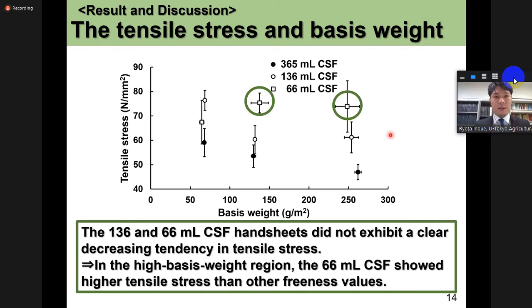This figure shows the relationship between the tensile stress and the base weight of single-layered paper prepared with different freeness values. The 365 milliliter CSF hand sheet showed a negative correlation. However, I'd like to stress that as the refining progressed, the 136 and 66 milliliter CSF hand sheets did not exhibit a clear decreasing tendency. In particular, in the high base weight region, the 66 milliliter CSF hand sheets showed higher tensile stress than other freeness values.